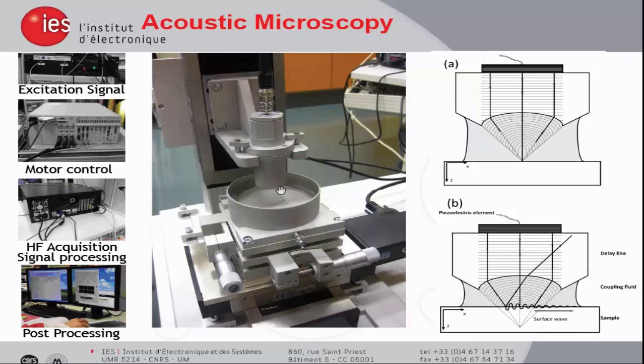So here you've got a scheme of the sensor with a piezoelectric element that is deposited onto a silica delay line, at the end of which you have a lens, acoustic lens, that will focus through the coupling medium the acoustic beam onto the surface of the sample. So when you move the sample, for example, with respect to the sensor, then you can dot by dot reconstruct an image of the reflectivity of the sample. Then, if you lower the sample, you can focus the acoustic beam in the depth of the material to have an image of this depth, or you can also work on the characterization. The first two imaging protocols were made to control the material to see if there is any difference or any defect.